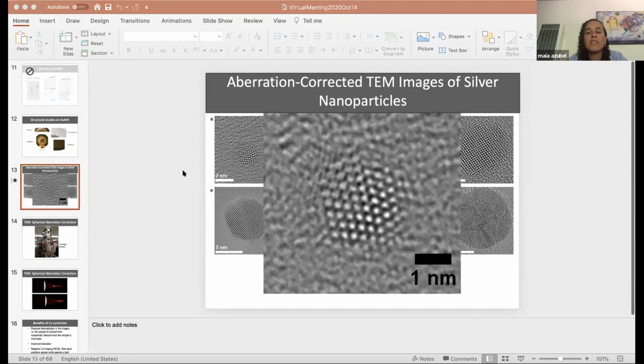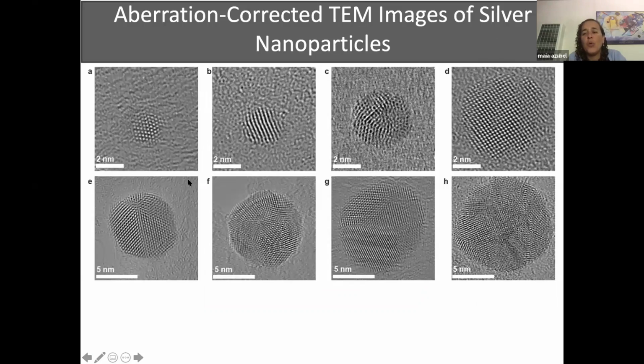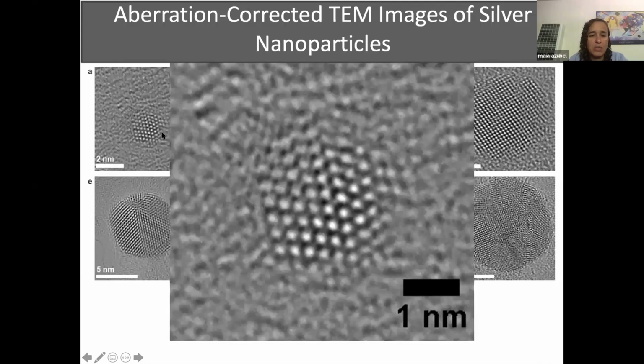So there are a couple of ways to answer. One of the reasons why the larger clusters especially look so good is that the amount of dose that they use to image them is very high. That's one of the reasons you get such nice images. You can see that also in this small one, where you see very clear atoms.